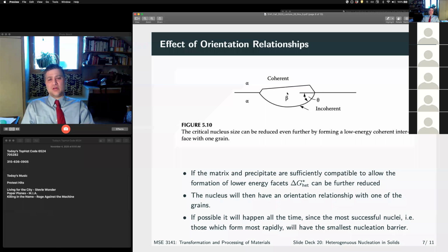Almost every particle that we see will have this orientation relationship. 100%. Because of the statistics, we're relying on random, thermally driven fluctuations to put our atoms in the correct configuration. The number of atoms is huge, and the number of times this is happening is really, really large, 10 to the 11th per second in terms of vibrations, somewhere around that order.